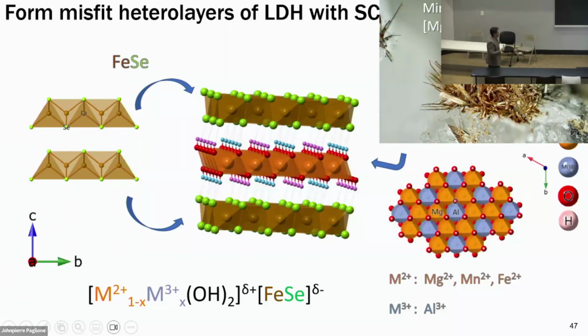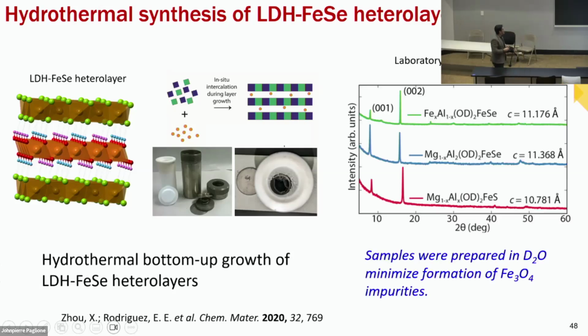And unfortunately, we haven't quite gotten to a superconductor in this one because it overdopes. This hydroxide layer puts too much charge in here. But what's enticing about this is that you could put magnetic cations in here and eventually make a magnetic layer that's proximate to a superconducting layer. So that's something we're still working on. And again, it's done hydrothermally.